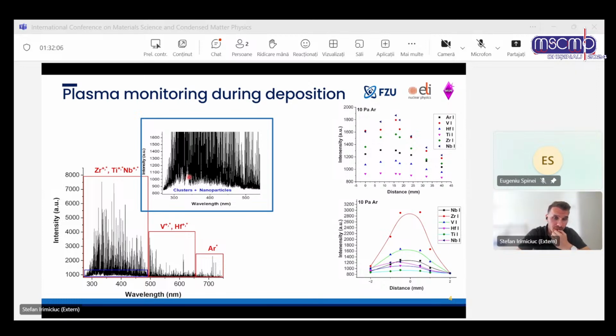And also to point out that the spectra also give us an idea of the fact that we have clusters and nanoparticles. I don't have a film here to show you, but when we do the deposition, we can actually see these metal nanoparticles flying away from the target, and it acts like a splash on the water. If you hit the water with your palm, the droplets will go outside. So this is something similar that happens during the PLD.